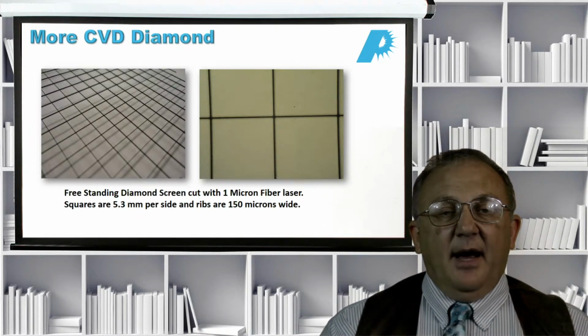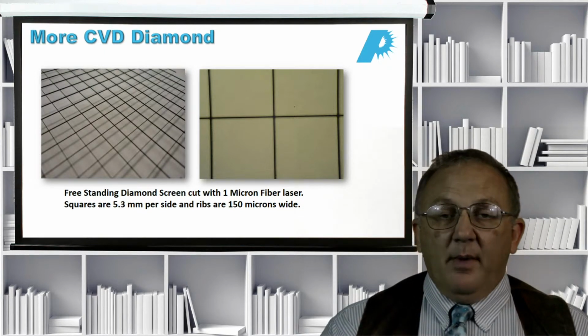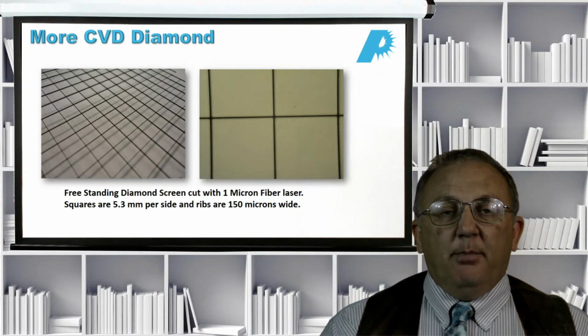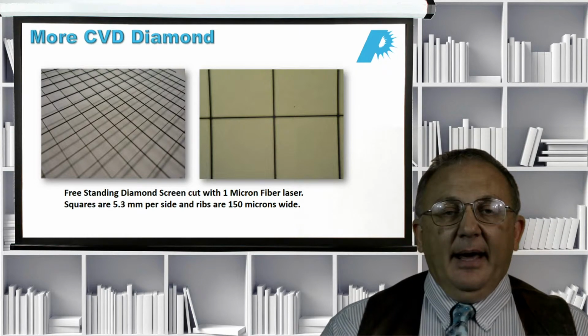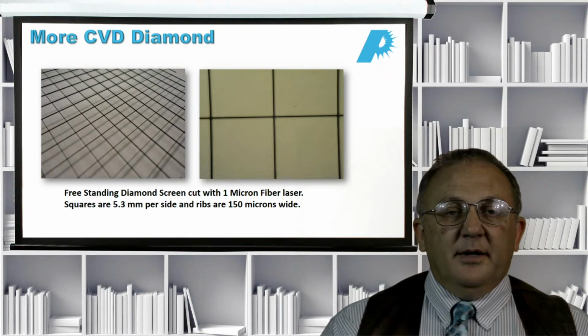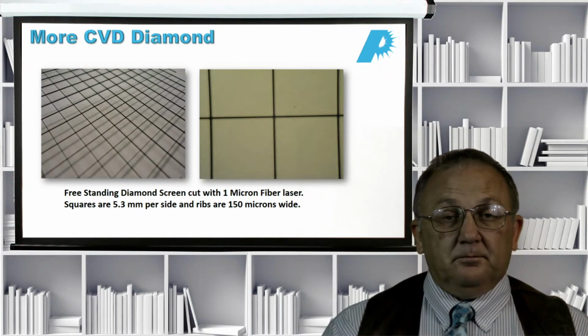Some more pictures of CVD diamond. This actually is a freestanding diamond screen made with a 1 micron fiber laser. The actual parts that we cut for the customer were the squares that were taken out, and this freestanding screen was what's left over. So the squares are about 5.3 millimeters on a side, and the ribs are about 150 microns wide, and on the order of a couple hundred microns in thickness. So you can see we've still got a lot of mechanical stability there, even though the feature sizes are extremely small.